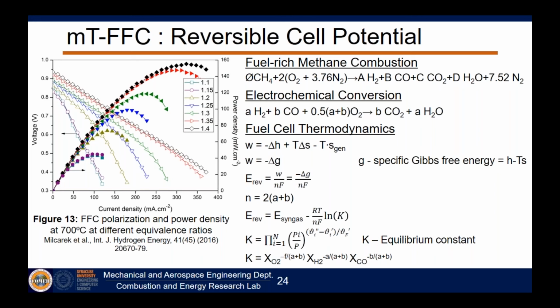And so the reversible cell potential is related to a reversible cell potential for the syngas composition minus the effect of the dilution. And so this term right here basically says, well, we've got to get rid of the fact that we have carbon dioxide and nitrogen that are diluting the fuel. That's an equilibrium constant. We can relate that to partial pressures. I can spare you all the math.